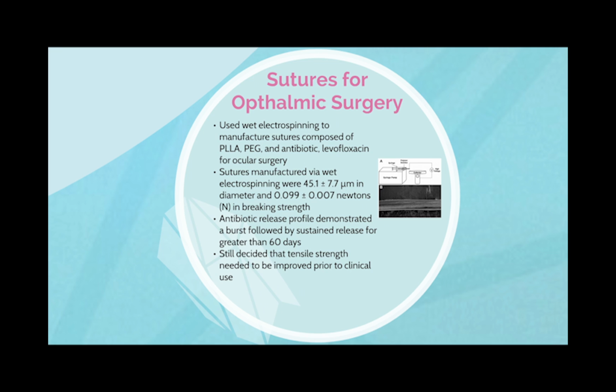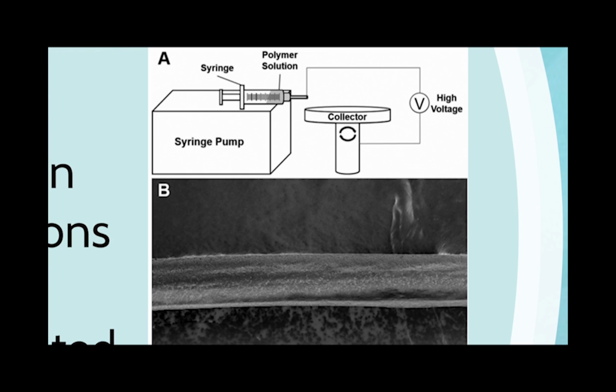From this, they actually decided that the tensile strength needed to be improved prior to clinical use, which is important to note since our device would solve this issue. And they also showed that the antibiotic release profile demonstrated a burst followed by a sustained release for greater than 60 days. This image shows the wet electrospinning method and what a typical suture from this method looks like.